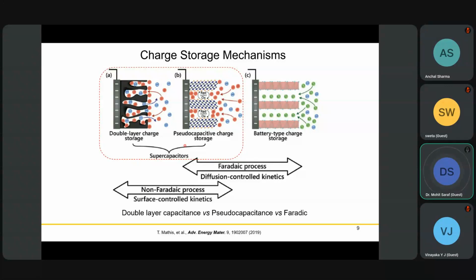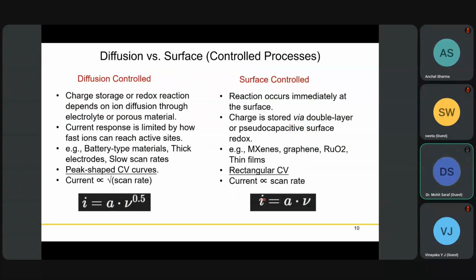When it is a surface control reaction, basically we talk about supercapacitors, then it's a non-Faradic process, and it's a surface control thing which is very fast. And when we talk about the Faradic process, which is typical of batteries, we have diffusion controlled kinetics with limitations. This diffusion control thing is typical of battery type materials, where the response is limited by how ions can reach the active sites. With these formulas, current versus scan rate, we can estimate whether the process happening is diffusion controlled or surface controlled.